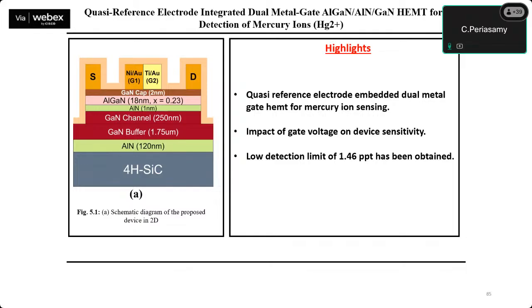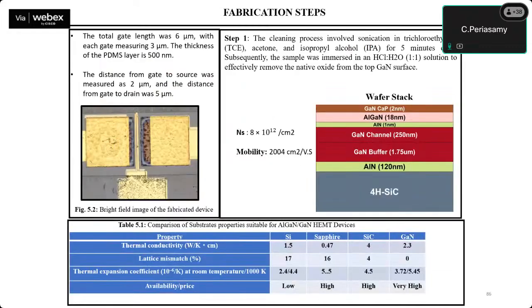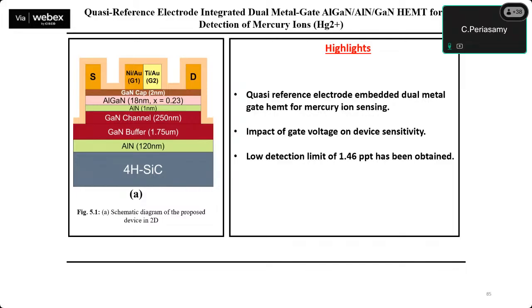So this is the structure we have used to detect heavy metal ions present in the water. Whatever structure we proposed for pH, here we have used a different structure for heavy metal ion detection. We have fabricated the same HEMT structure for heavy metal ion detection here. Instead of silicon, here we have used silicon carbide as a substrate.